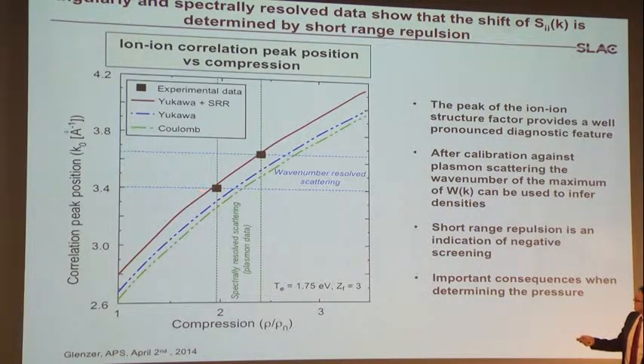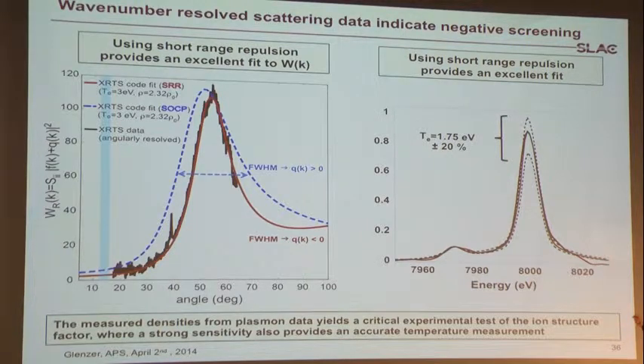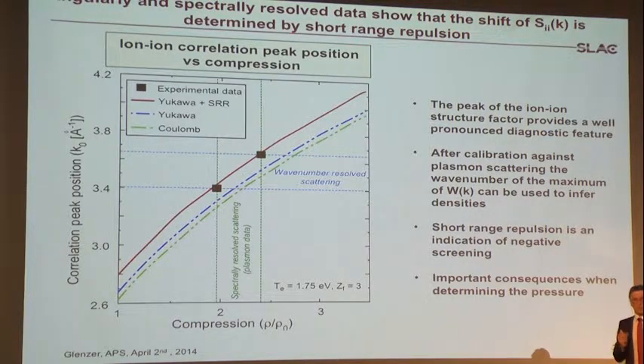So what we find is we have the peak position, and we have the compression from our plasmons. And again, we find that the screened Yukawa potential plus short-range repulsion agrees very well with our experiment. And that's why we believe we can get the ion temperature from our plasmon scattering spectrum. That was shown here. This is again our variation of ±20%, and we have the theoretical approximation that lets us derive the temperature in this case. So, besides temperature, structure factors are generally important for warm dense matter.